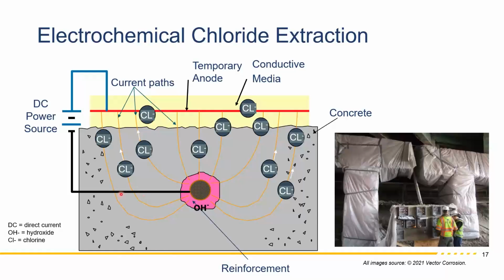So this is similar to cathodic protection, except in cathodic protection you don't have a temporary anode, you have a permanent anode, and you put less current, about 10 milliamps per square meter, compared to about 1 amp per square meter here. You basically keep the steel from corroding. That's the threshold where corrosion doesn't happen. But you have to make this a permanent connection. You have to have rectifiers to make sure that the current is constant, because there's temperature dependency and moisture dependency. So it's an involved process, cathodic protection, but it's well worth taking a look at, especially in marine environments and splash zones and so forth.